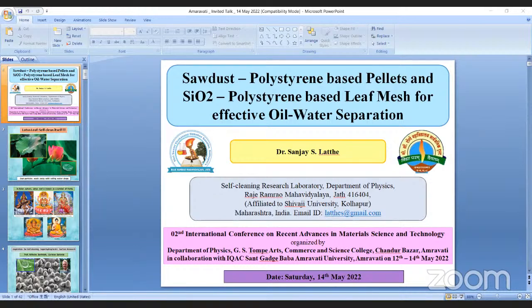So the mechanical durability of the superhydrophobic sawdust pellets was also checked. For this, we use the adhesive test and the sandpaper adhesion test. For this test, the pellet shows high mechanical durability, and it is superhydrophobic in nature.